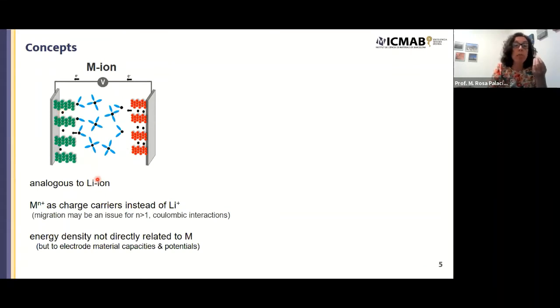And in this case, the energy density is finally dictated by the potential difference between the two electrodes. So it is not really related to the nature of the metal, but one has to bear in mind that the limit for this negative electrode is the limit for electrodeposition of the metal. So this is one thing. And another thing relevant to mention here is that for the charge carrier ions that have a charge higher than 1, there may be some issues both for the migration of the solvated ions in the electrolyte and also for the migration in the solid state. And about this concept, I will mention the development of sodium ion as an example. One of the advantages here is that you can take advantage of the know-how developed in the lithium ion technology. And then you can expect a faster progress.